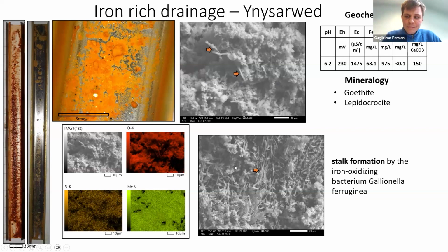And in the bottom right picture here, we can see that those stalk-style formations might represent most of the ochre material that precipitates on the surfaces. So it was very interesting to see that there is a magnitude of how much iron-oxidizing microorganisms can contribute to stalk formation. On this site, just to mention, there is no corrosion issue. So at the classic iron site, we didn't find corrosion.